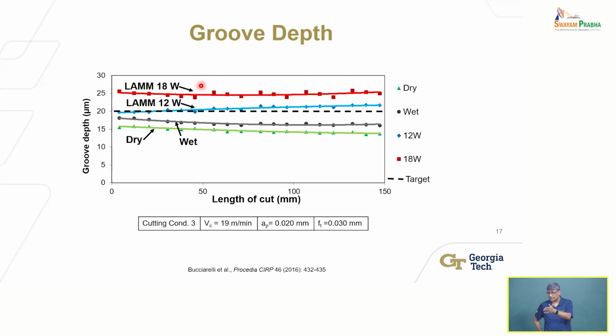Yes, conduction, but somebody said the word thermal expansion. When you heat something up, it's going to expand. So what's happening to the workpiece? In addition to softening, it's expanding. And you're producing pretty high temperatures. 18 watts over 280 microns, the energy densities are pretty high. Right at the center of the laser spot, it probably is ablating some as well, but not ablating everywhere else because it's a Gaussian distribution, so it has a steep decline in energy. But bottom line is it's also expanding thermally.